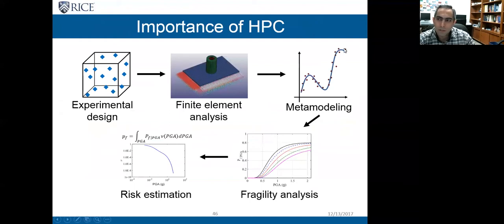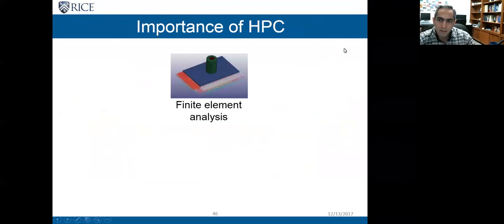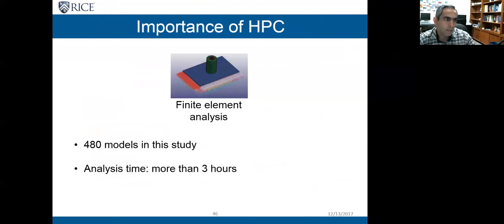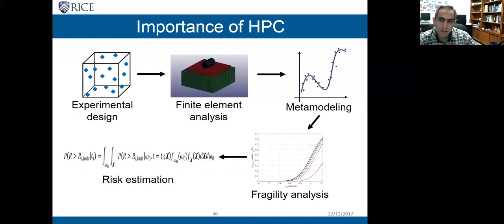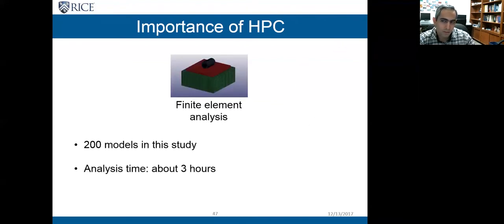So this is the workflow that I showed you before. And I had to use high performance computing for running my models. In the seismic analysis part, I had about 500 models, and each of them took at least 3 hours on 96 cores. For the tip over analysis, I had 200 models, and each of them took about 3 hours, again on 96 cores. And this means that without high performance computing, I was not able to do this research.